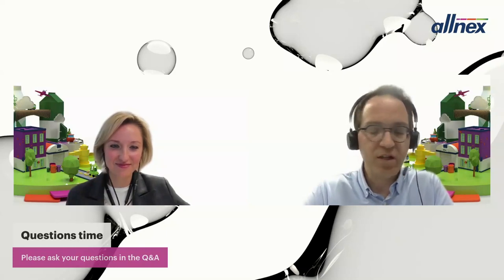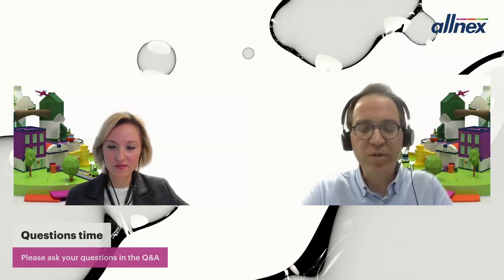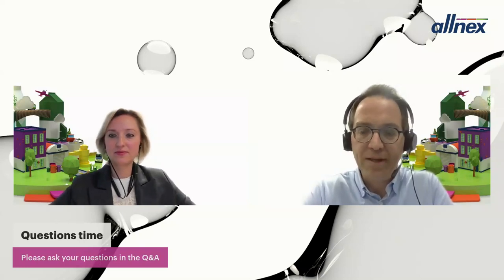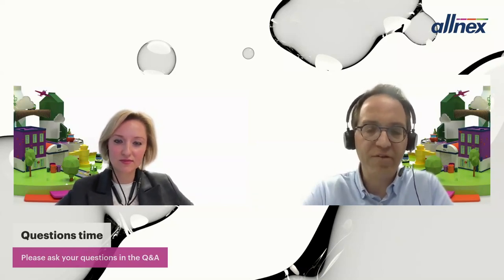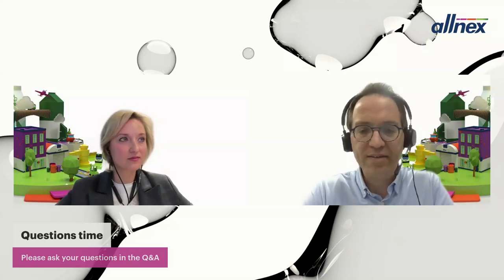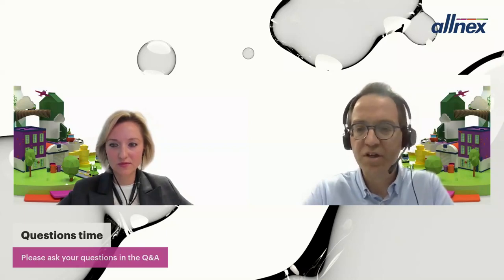To be short, yes. We have actually quite a good track record when it comes to outdoor durability. I think I mentioned during the presentation that we're looking at a fully aliphatic system, which helps. From our own testing, both in accelerated weathering and in real-life weathering in Florida, we get very good results, which are at least on par with high-end 2K PU systems, for example. And we get good feedback also from customers looking into those aspects. So I have no fears on that side.